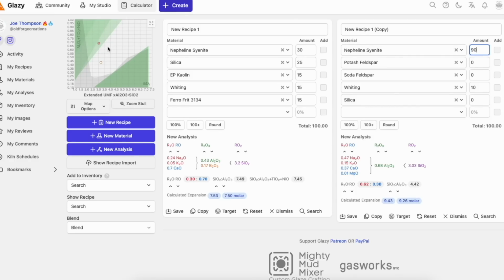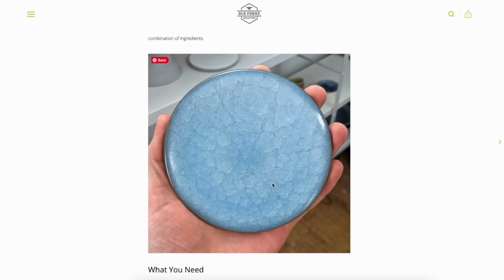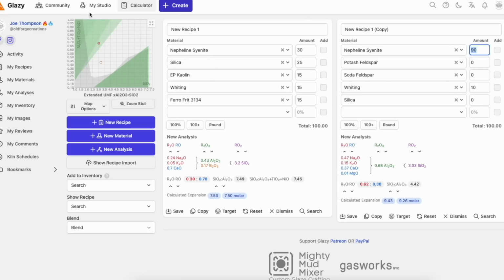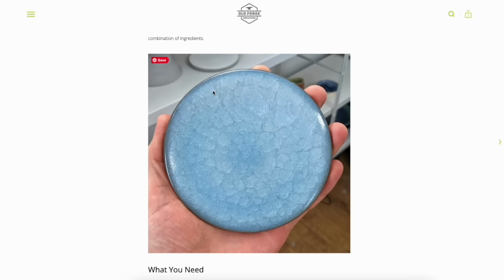But yes, you get that pattern because you've got extreme shrinkage in a kind of matte-ish glaze, but that's a very extreme glaze, and you wouldn't use that to be durable. It does work and produces a really cool result. It's a pain to work with for studio problems. So the glaze gels in the bucket and you can't get it onto the pot, and if you do get it onto the pot, you've got to get it on so thick that it then crawls back off the pot and falls off before you get it into the kiln.